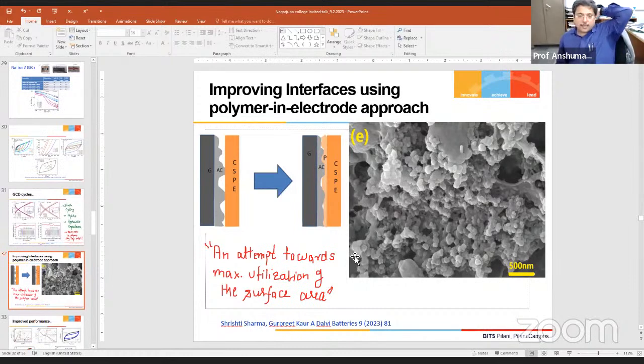Last topic, 5 minutes more I'll take, and I'll be winding up. Interface is still important, and the solid-solid interface is something which requires more understanding, more physics, and more support from theoretical input also. And you have to play with this interface. One of the ways people do this at the interface is by incorporating some kind of buffer layer. The way you put butter between two bread slices, and it sticks. That way, nowadays people are using various buffer layers between an electrode and electrolyte. To stick a solid electrolyte and electrode, you have to use a good buffer layer.